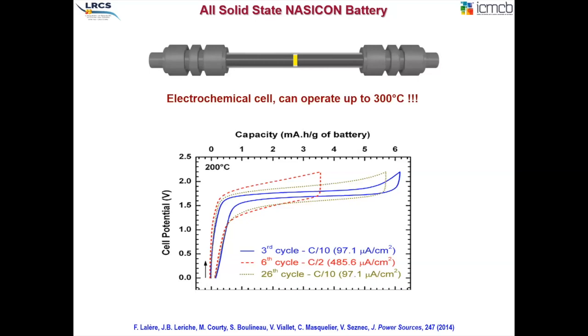The performance was satisfactory, I would say, not to mention here that these were measured at 200 degrees Celsius, but still feasible, and several groups are working on trying to improve these numbers in solid-state batteries that do not contain any sulfur and that are purely made out of oxides. And in this case, with the NVP on both sides, it's a full Nasicon structure solid-state battery.